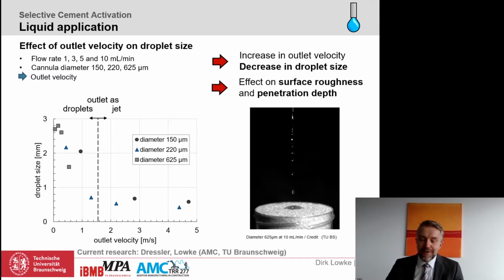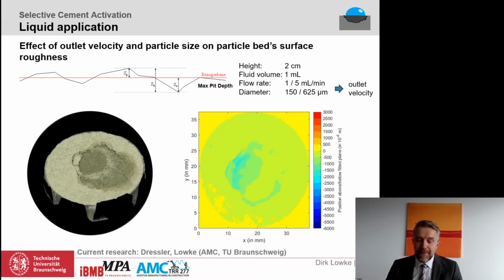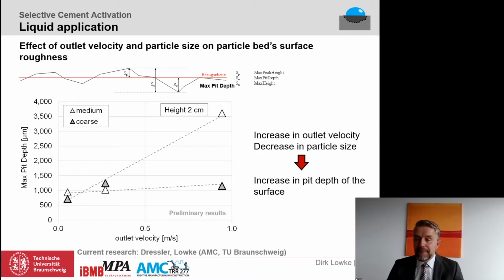Well, this knowledge is now the starting point for the next sub-process, the impact and penetration of the water into the particle bed. Let me start here with the effect of the outlet velocity and the particle size on the roughness of the particle bed after the water has impacted the surface. Here we use the digital microscope to characterize the surface texture. And for the sake of simplicity, we have defined the maximum pit depth as the characteristic value for the surface quality. And as you can clearly see in this diagram, with increasing outlet velocity, the maximum pit depth increases. However, if we use coarser particles in the particle bed, as you can see here in the gray symbols, then we can really attenuate this effect.